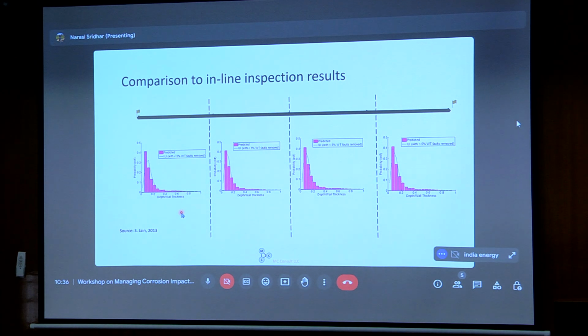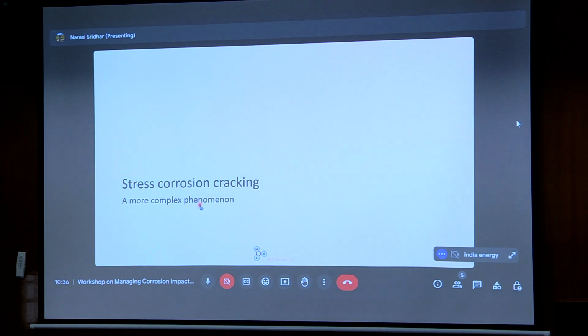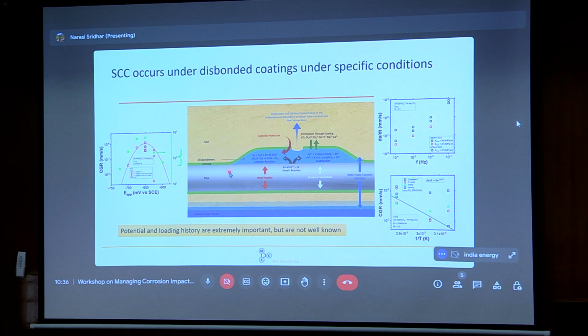against existing field data. Stress corrosion cracking is a much more complex problem, mainly because you now have a load involved and you have coatings involved. So stress corrosion cracking invariably happens under a disbonded coating. The coating adheres throughout the pipeline, but at certain locations, the coating tends to come off, called the disbonding process. And in this location, the water from a hole in the coating accumulates and you get reactions. That's because the cathodic protection doesn't permeate all the way through into this region.